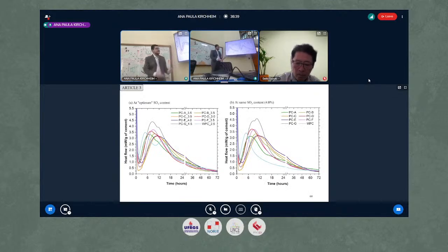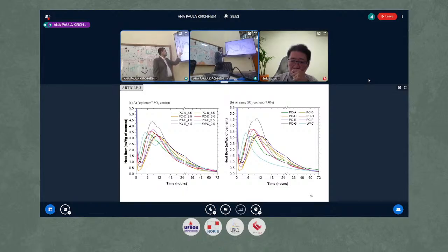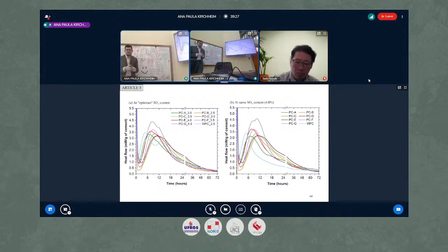So here we have all the calorimetric curves at the same SO3 content, 4%. We see the great difference between the clinkers, in the induction period and the silicate peak, and here I highlight PCG that has the highest silicate peak. We couldn't find an explanation in the mineralogical composition of this clinker. Perhaps it is due to uncontrolled factors such as quenching, that can promote different effects on alite crystals and increase alite reactivity, so due to process parameters that we didn't control in this research.